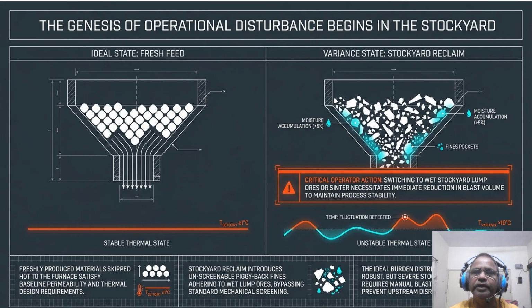On the left, the ideal state shows fresh feed with a stable thermal variance of plus minus 1 degree centigrade. But look at the variance state on the right. Notice the moisture accumulation exceeding 5% and the blue shaded fines pocket. This is not just a material issue, it's a thermal disaster. So when you switch to wet stockyard lump, you are essentially injecting a thermal heatsink into your top.